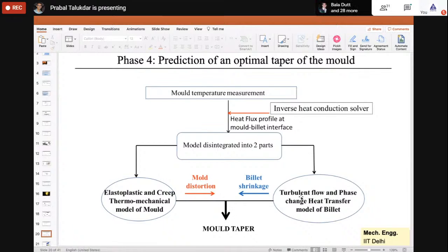Here we have not done any mechanical analysis because from the temperature distributions itself, there are standard relations available, which we have used here to find out the shrinkage of the billet. Of course, we can do a small mechanical model here also, but that requires more involvement. So for the time being, instead of a mechanical model, we have used standard relations to find out the billet shrinkage from the temperature data. Now you have the billet shrinkage and mold distortion. Both these deformations are present, and from that we have predicted the mold taper. That is the final goal which we have done in this problem.